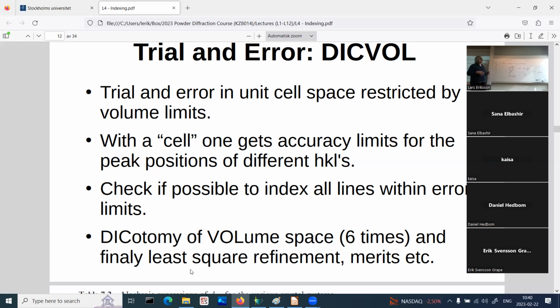In the worst case, there could be some non-linearity. If the unit cell is refined to a considerably different position than the starting position, then maybe the HKL values are changed for the lines, and then we will have an oscillating refinement, but that is less of a problem compared to structure refinement. Otherwise, you need to check it.